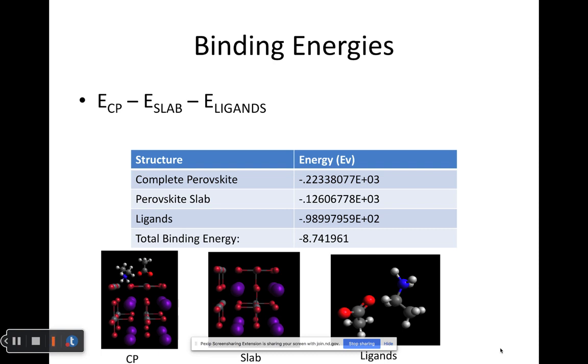Is two ligands sufficient to compensate for potential dangling bonds? No. One needs enough to have complete monolayer coverage. For this model, I do not see it from here, but it would need something like 4 anions and 4 cations on the top, and 4 anions and 4 cations on the bottom, to cover the slab everywhere it interfaces with vacuum.